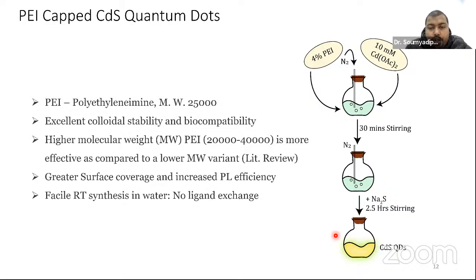So what we did, we took a branched polymer, a dendrimeric polymer, polyethylenimine, which has a molecular weight around 25,000, and we synthesized these cadmium sulfide quantum dots in water at room temperature. These are the two main things. First, we synthesized directly in water, so there is no question of ligand exchange. And number two, this is at room temperature.